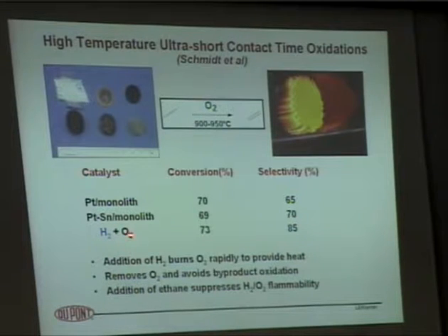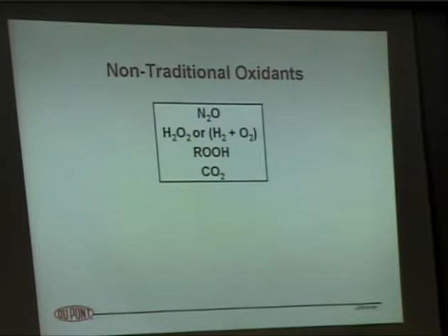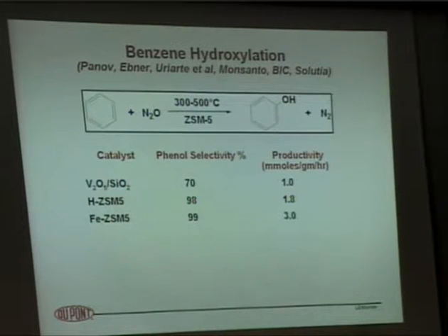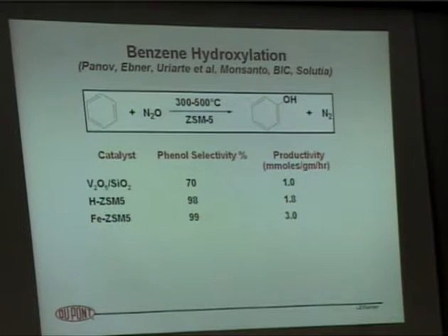The hydrogen is used to combust the oxygen in the process to provide the heat to do the dehydrogenation of ethane to ethylene. So the hydrogen removes the oxygen, so it's not available for the high temperature, radical catalyzed, non-selective reactions. And he's able to get 85% selectivity to ethylene from ethane at nearly 1,000 degrees centigrade. So clearly a new out-of-the-box way to do things. So let's move on to these non-traditional oxidants. I think there's a real opportunity here as we move ahead.